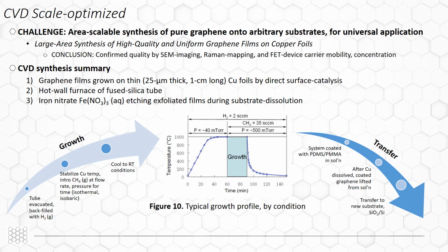The growth process began by evacuation of such foil-loaded tube whose original pressure was replaced by that of hydrogen gas at 40 millitorr, added at a maintained flow rate of 2 sccm for the entire process at 1000 degrees Celsius. The temperature of the copper foil substrate was finally stabilized at less than or equal to 1000 degrees Celsius during this typical conditioning pre-process time interval of about 60 minutes.